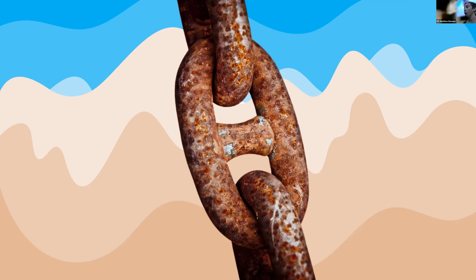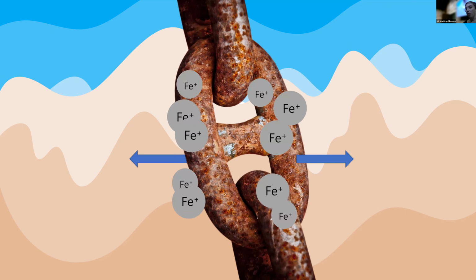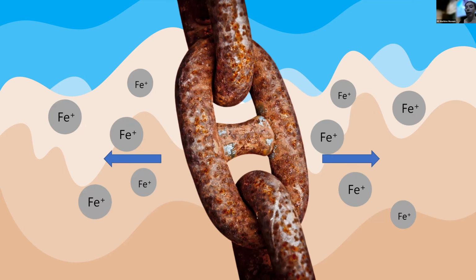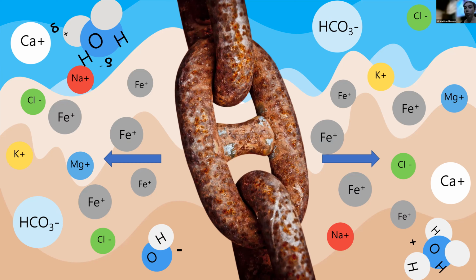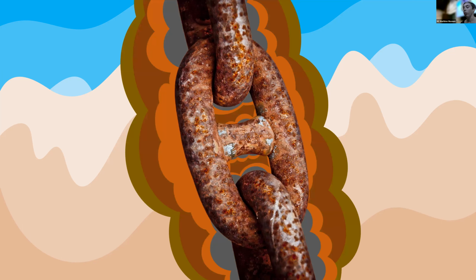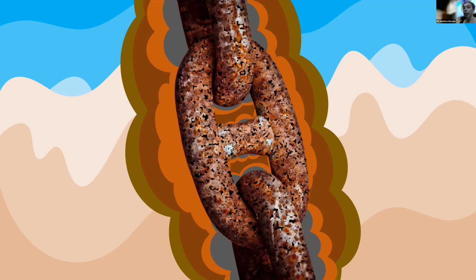So how this might look in an underwater burial environment. We have our iron chain, it's buried in the ocean, under several layers of sand. The sand is actually wet, there's water in the sand. It's almost a mixture in some areas, depending on how boggy it is. So you have access to oxygen and water and electrolytes in the environment. So what you're going to have is corrosion of your artifact. You're going to have the release of these metal iron cations, these minerals that are leaving the artifact, essentially moving directionally into the environment. They'll come in contact with other dissolved minerals, which will then form your corrosion products. You'll have these successive formations of different types of mineral content being layered on top of your artifact, to the point where sometimes you might actually no longer have an artifact.